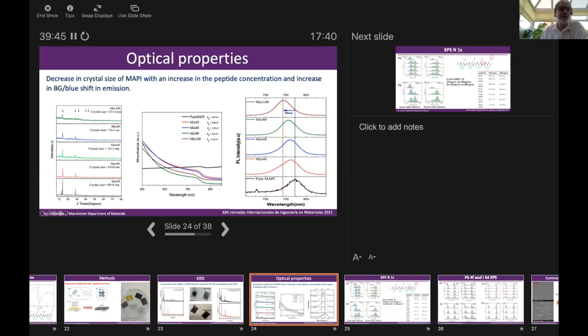And you can see in each of these cases, the width of the diffraction peaks increases. And if we use the Scherrer formula, we find that we're actually getting a decrease in crystal size. So the pure MAPI has a crystal size of about 70 nanometers, but by the time we've mixed it with 100 mg per mil of peptide, we've decreased the particle size to about 27 nanometers.